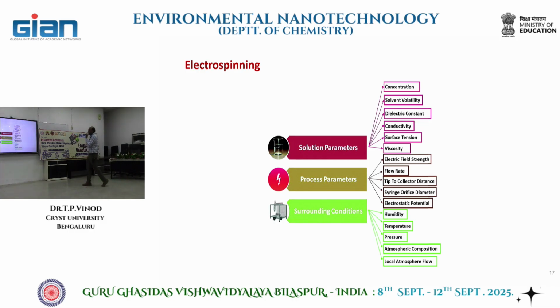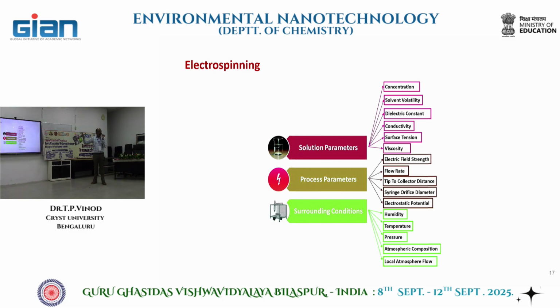Then what are the things you need to optimize for this? You need to optimize three different parameters. One is solution parameters, another is process parameters. The final one is surrounding parameters, the surrounding conditions. About the solution parameters, you need to control the concentration, how many grams per milliliter you are dissolving in the solvent. And then solvent volatility, how volatile your solvent is. Then the dielectric constant of the solvent. Is it polar or non-polar, and is the polymer polar or non-polar?